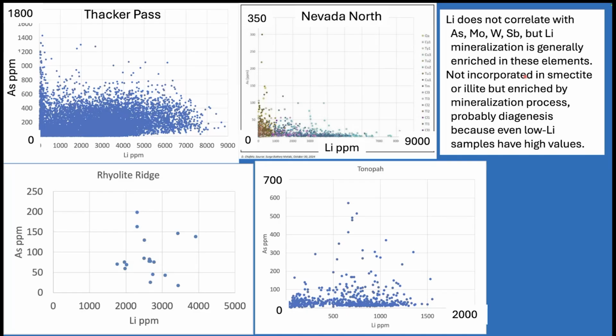Arsenic, the lithium deposits are definitely enriched in arsenic. You can see at Thacker Pass, you get up to more than 1,400 ppm. Nevada North, 300, not terribly high, but that's significant. Tonopah up to nearly 600 ppm. Not all that enriched in Rhyolite Ridge, but 200 ppm is definitely arsenic enrichment. However, there's no correlation between the arsenic and the lithium, which says that the arsenic is enriched by the process that generated the lithium mineralization, but it's not incorporated in the lithium clays. It's probably gone into pyrite, arsenopyrite, other sulfide minerals.